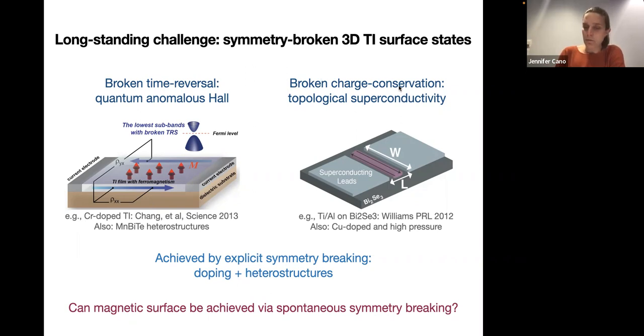And the other thing that you can do is break charge conservation. And this really means inducing superconductivity. And it turns out that the superconductivity you can get on the surface of a topological insulator becomes a topological superconductor. And this has many exotic effects. And this has launched the search for Majorana fermions. So superconductivity on a topological insulator has been realized also in a few different ways, by making heterostructures and by doping with copper. So for both of these cases, we can realize these broken symmetries by explicitly breaking the